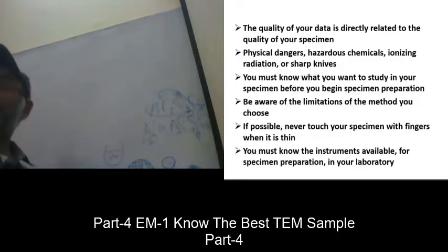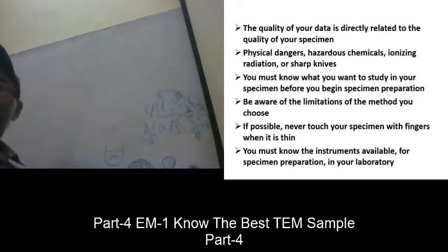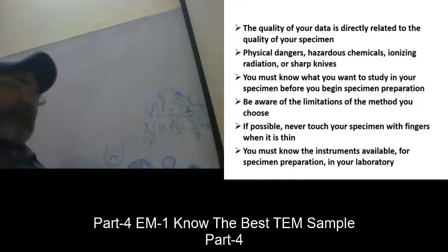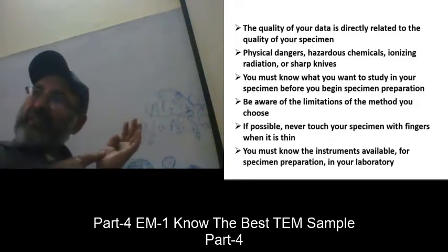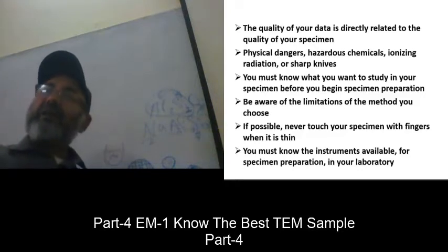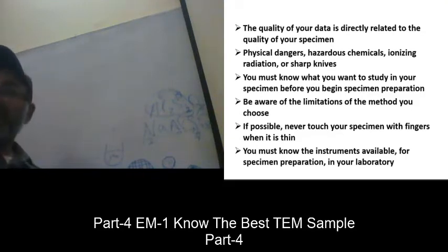So it is a chance, and people usually get that chance. I prepared all these sorts of samples, and when you prepare 3-4 samples, then there is a chance that you will find some electron transparent sample and you can use it. This way is quicker, that you put a copper ring, fix the sample upon it, thin it down, and when you are experienced and skilled, you thin it down to the desired thickness and very easily prepare the sample. But here you are limiting the area.